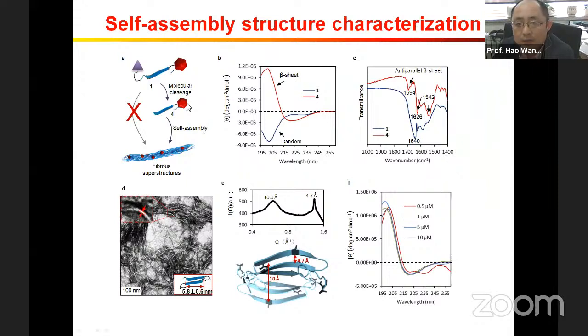So when we add the enzyme to this molecule, we can see the molecule self-assemble into very defined fibril structures, with a layer distance of roughly 10 angstroms and a single strand distance of about 4.7 angstroms. It's quite clear. More importantly, in this concentration dependent study, we realized this aggregation can happen at very low concentration, even below 1 micromolar. That means this molecule is very sensitive to aggregation.